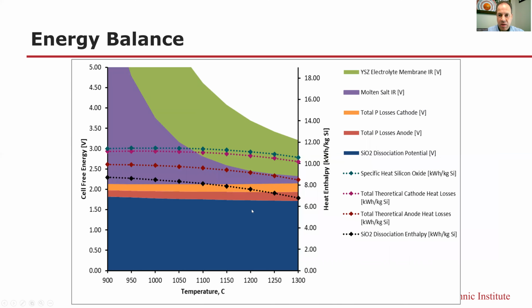So we have the dissociation potential, which is the free energy divided by the Faraday constant. And we have other losses here in the anode and cathode leads, in the molten salt, and in the zirconia electrolyte. So we essentially have two electrolytes here: the liquid electrolyte and the solid electrolyte. Those electrolyte losses drop very dramatically at increasing temperature. But nonetheless, we have to keep them above the heat balance here, because those result in thermal energy generation.